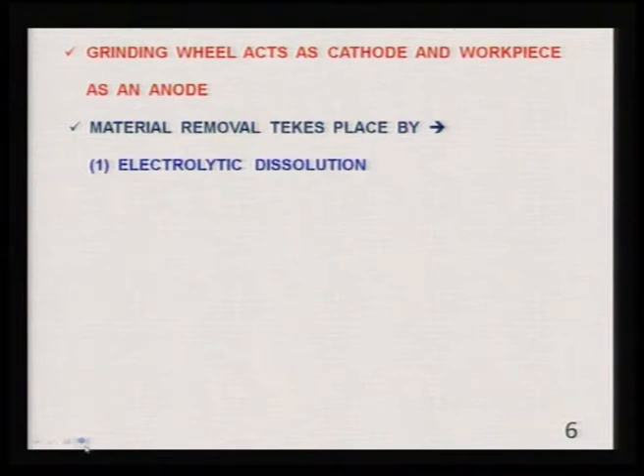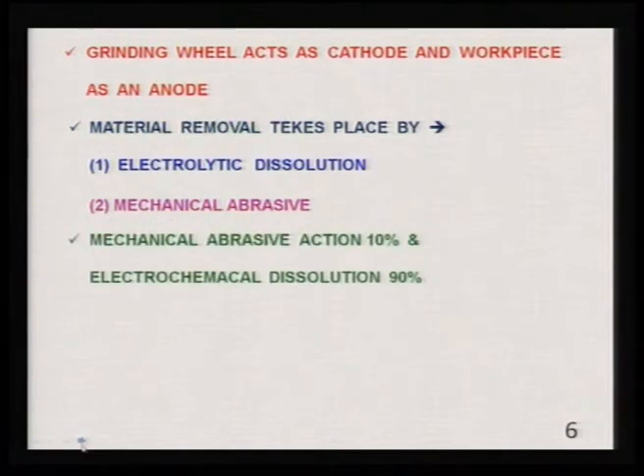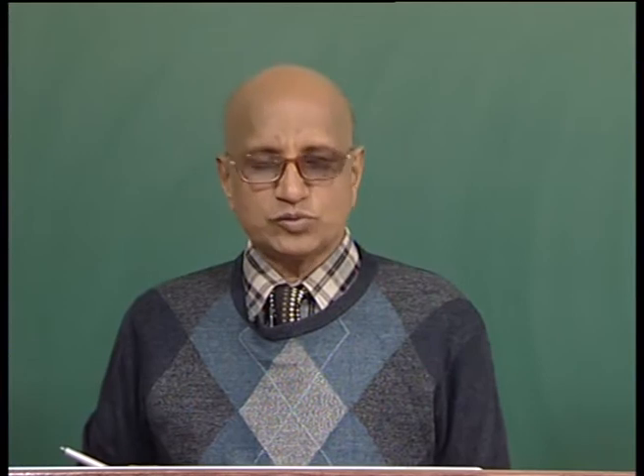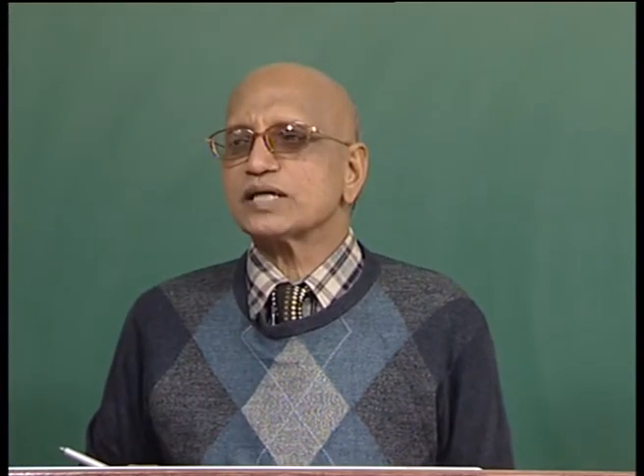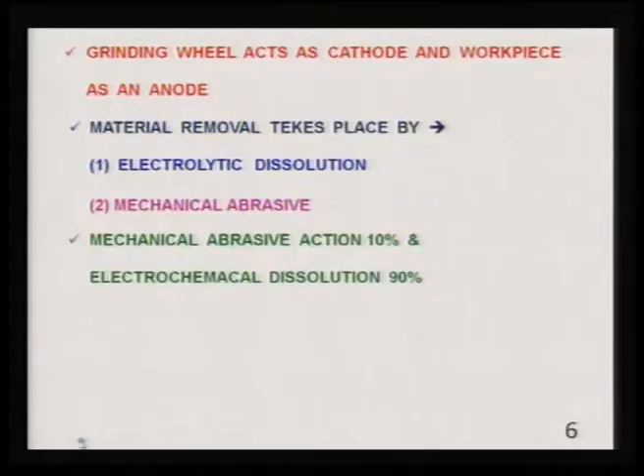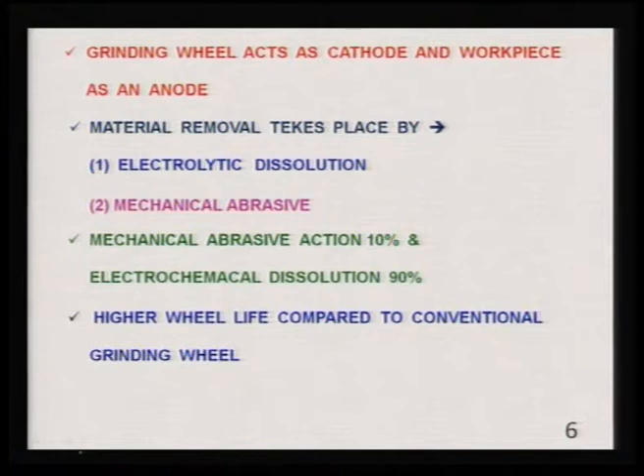Material removal takes place by electrolytic dissolution and mechanical abrasion by abrasive particles. They are part of the electrochemical grinding wheel. It is found experimentally that mechanical abrasive action is around 10% of the total material removal, while the remaining 90% is due to electrochemical dissolution, or as in case of ECM, where 100% removal of the material is due to electrochemical dissolution only. Higher wheel life is obtained in case of electrochemical grinding as compared to conventional grinding wheel life.